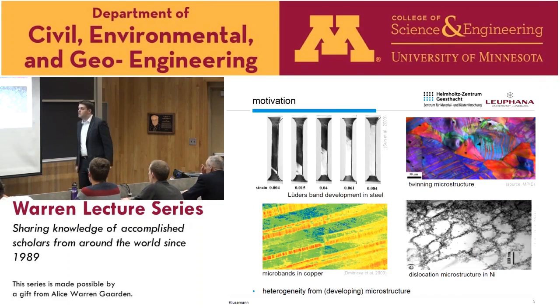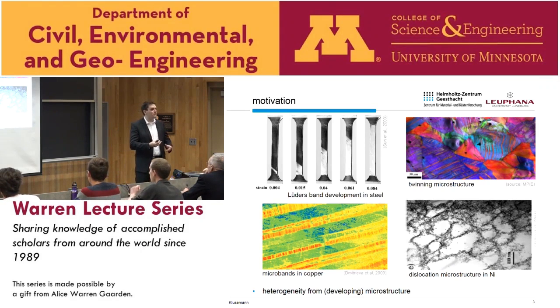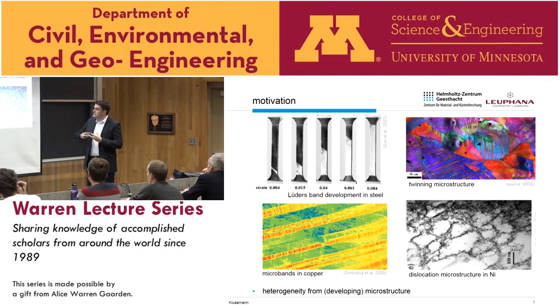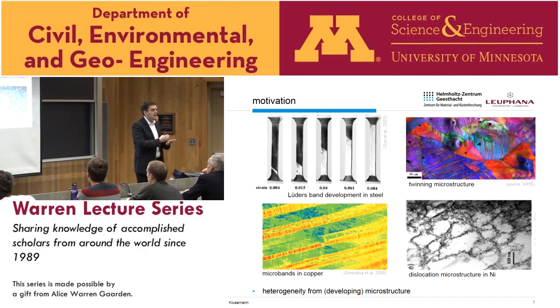But there is also another heterogeneity which I worked on in particular during my habilitation, which is the heterogeneity from a developing microstructure. So you don't have a constant microstructure coming from the production process or the composition in advance. You have a heterogeneity developing during the process actually. So one example is here, for example, Lüders band development in steel. You can understand it in the way to have initially a homogeneous distribution, but then you have a strain band which starts here. And this strain band then takes over in principle the whole macroscopic deformation you have at that time and runs through your sample until the Lüders band ends, and then you have again a continuous distribution.